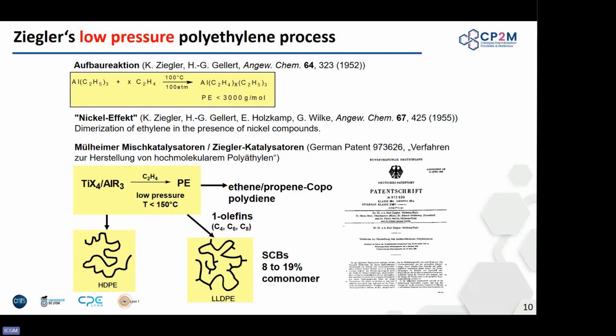So they started screening the periodic table, and they ended up with a mixture of titanium tetrachloride, TiCl4, and triethyl aluminum in the presence of ethylene at low pressure. You don't need to go to 100 bars, and they ended up with polyethylene. And then a lot of development for copolymerization. They realized that they could add a lot of comonomers, and they would be able, with only ethylene, to produce HDPE, and then with the comonomer LLDPE, with therefore a lot of short chain branching. Okay.